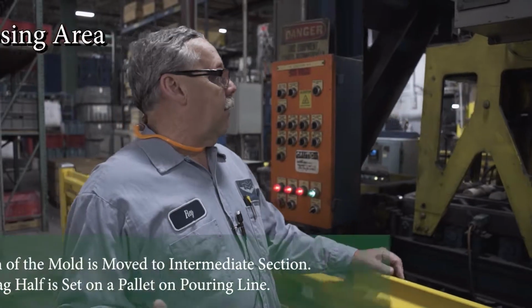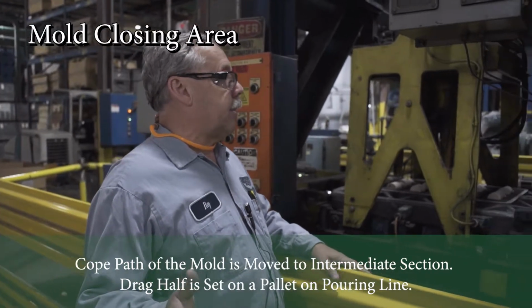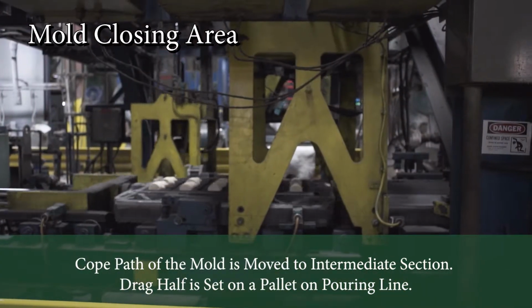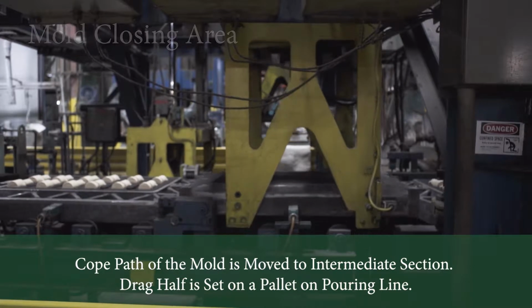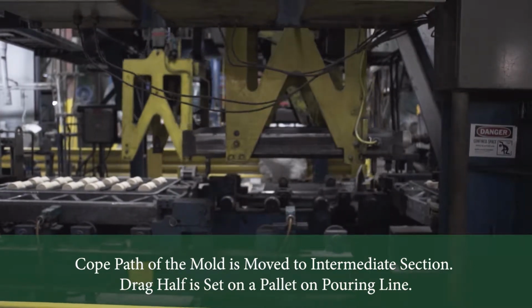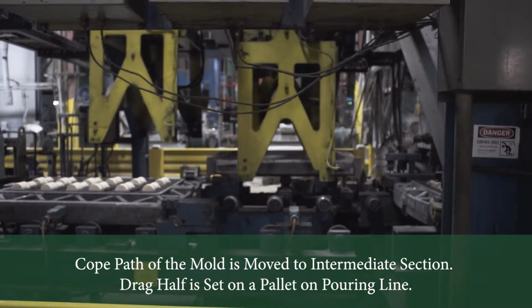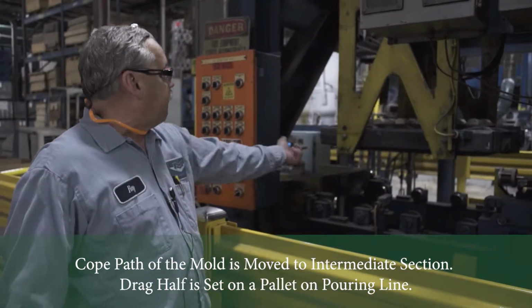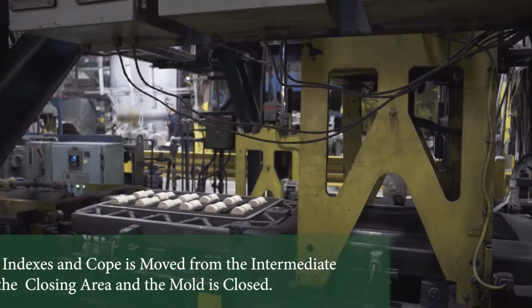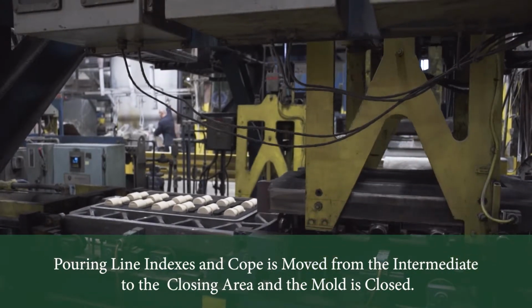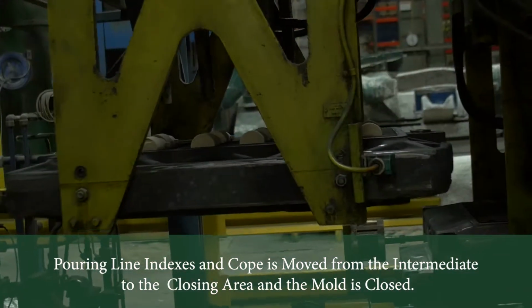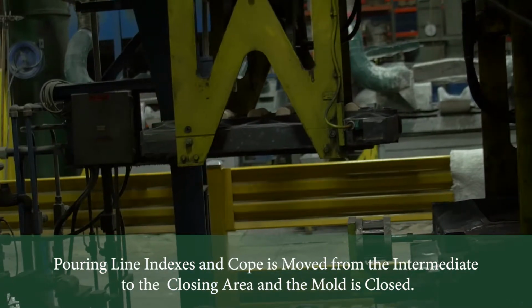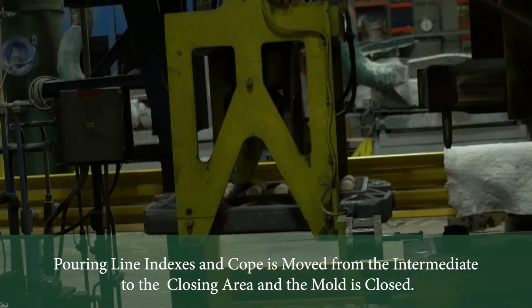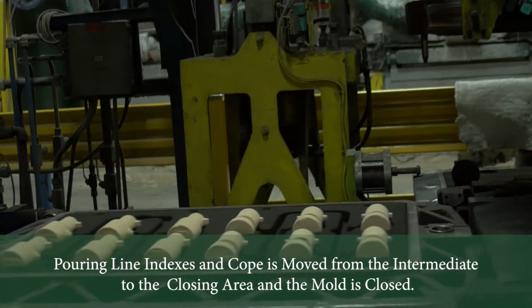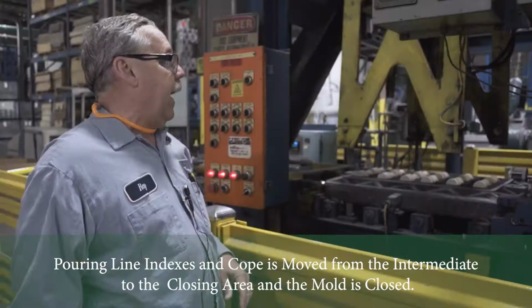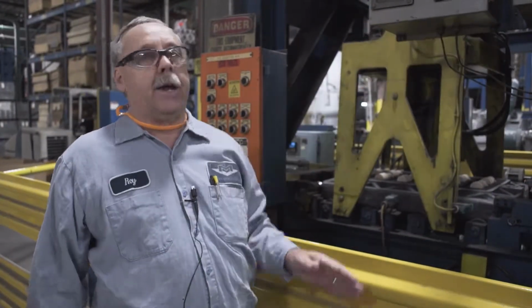Okay, this area here is where the two halves of the mold get put together. The cope half is picked up and transferred to an intermediate area. The drag will be picked up here shortly and transferred over to our pallet that just comes up from the base. There are pins on that pallet. We'll set that drag onto the pallet, engage it in the pin. The line will index. When the line is indexed, the cope half will be engaged into the bottom half, the drag. Meanwhile, the pouring is being done.